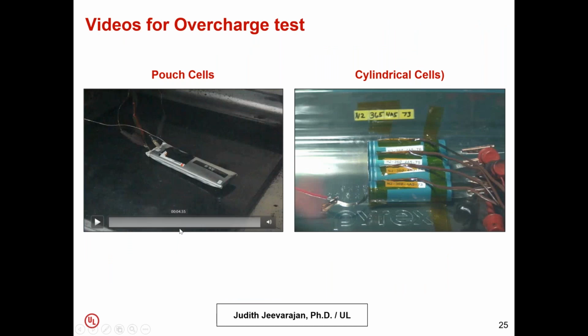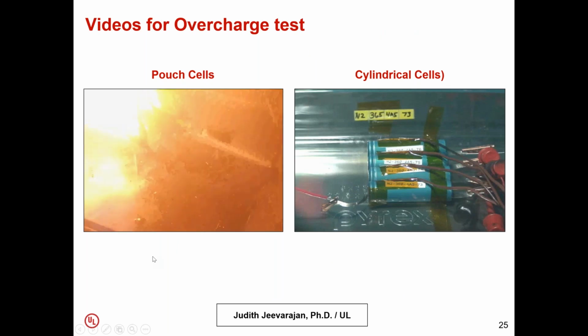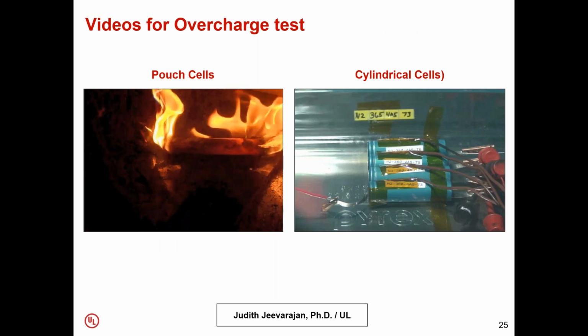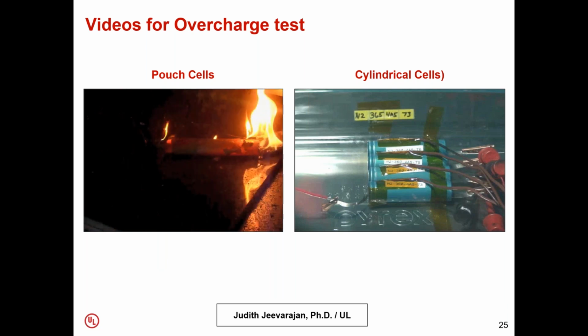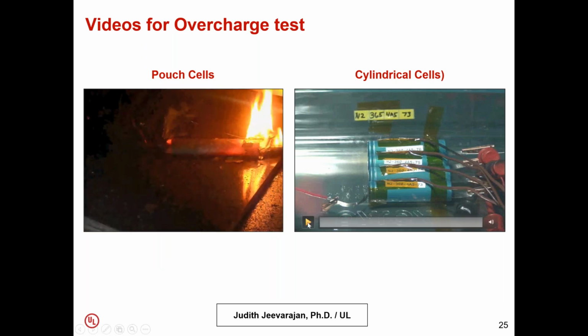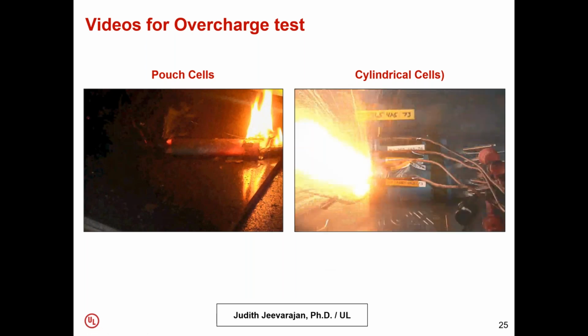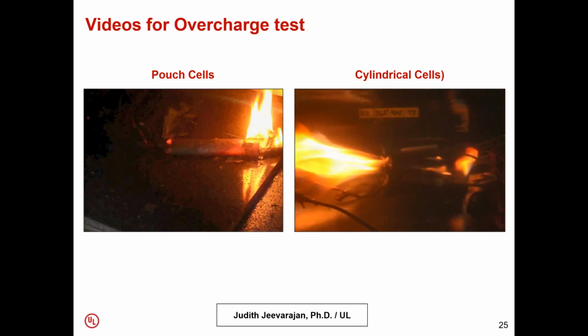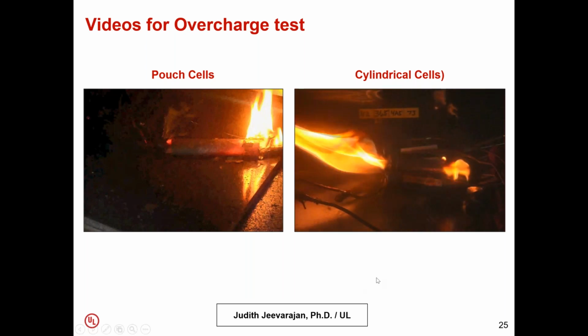So I just have a couple of videos that I would like to show. Sometimes people talk about pouch cells being very benign, but as you can see, because of the low pressures that a pouch cell has for bursting, it can give out liquid electrolyte or vapors that fall on the surface of a hot pouch and combust very quickly. So you can have a big fire where it burns till all the electrolyte is burned. This one is also showing you just 4 cells in parallel that have been tested under an overcharge condition. And as you can see, with even just 4 cells, you can have a catastrophic thermal runaway.